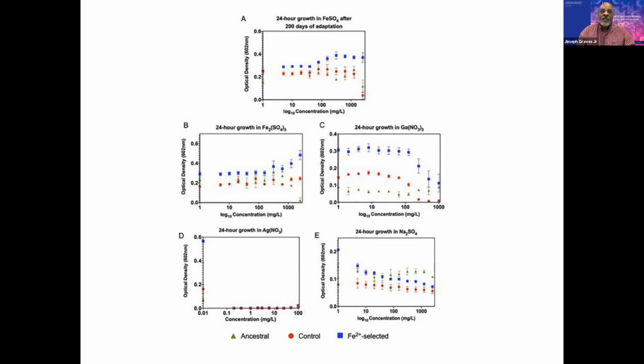So what we see from these results is that as we increase the concentration of iron 2, the iron 2 selected populations show superior 24-hour growth at all concentrations. The controls do slightly better than the ancestors, as we would expect, since the controls really aren't facing iron stress.